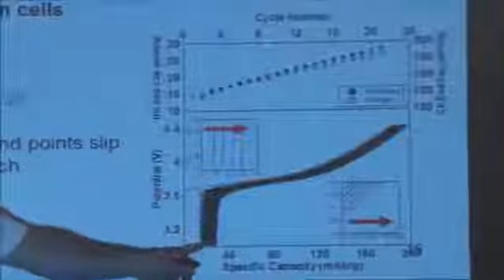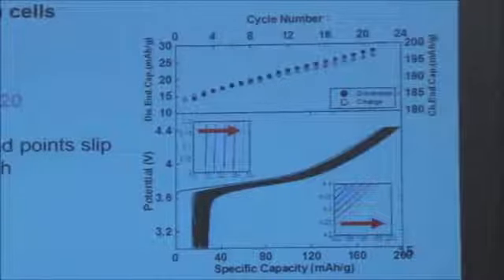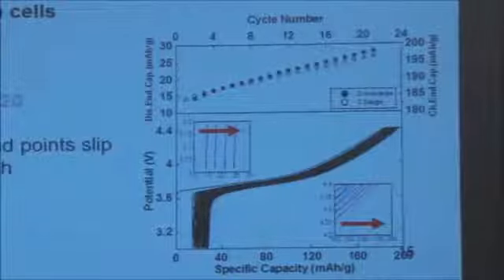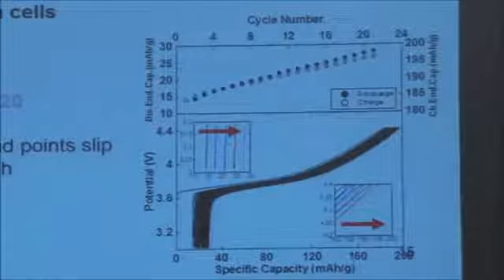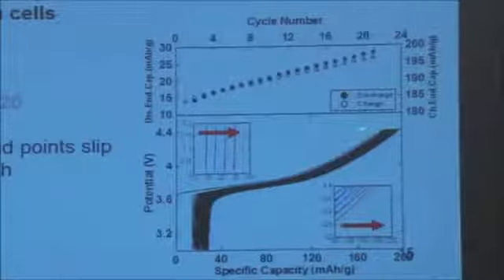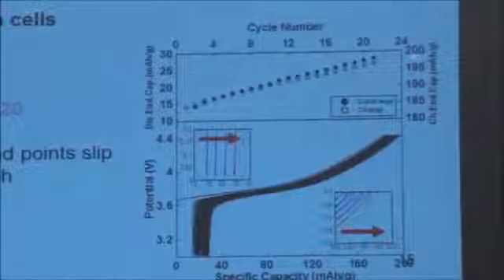And here we're going to just look at a lithium metal versus lithium transition metal oxide cell. Again, that's being charged, that's removing lithium, making the material more oxidizing, then add the lithium back, and it doesn't come all the way back to the axis. And every time you charge and discharge, the curve keeps shifting to the right. More and more electrolyte gets oxidized, and that oxidation of electrolyte causes the charge imbalance between charge and discharge. And the endpoints keep shifting to the right. And unlike the negative electrode side, this shifting doesn't seem to slow down. Okay, it just keeps increasing.